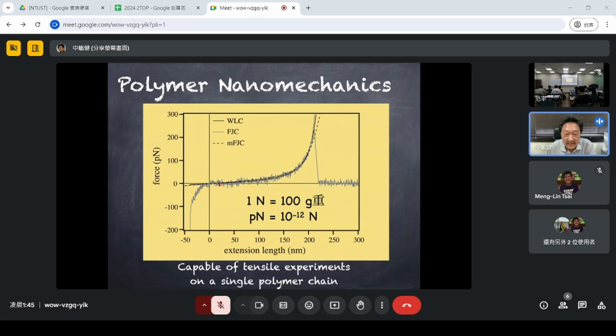And more importantly, as you can see at the beginning, you have a kind of proportional relationship between the extension length and the force. I mean that a straight line at the beginning was observed. So this is entropic elasticity experimentally observed. And here several different models are written. I will not go into the detail of that, but there are several models from statistical mechanics, for example the freely jointed chain or worm-like chain models, which can be compared with experimental results. So we are now at such a level. We have evidence that the single polymer chain has entropy elasticity, no problem. So the theoretical treatment was true.